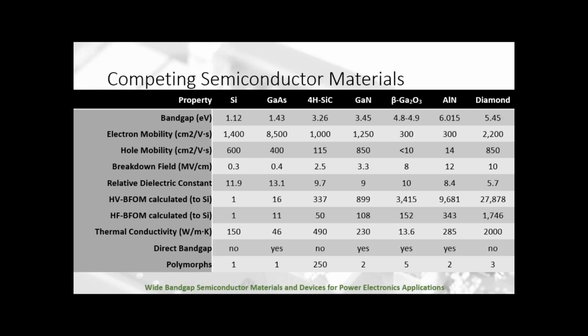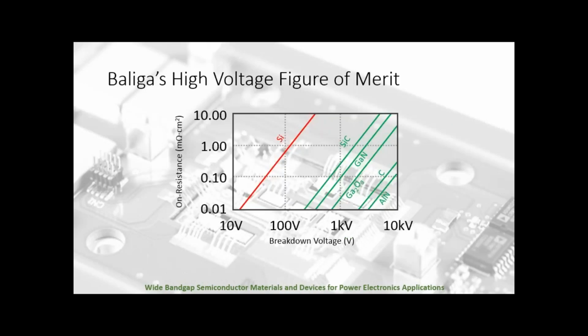Here, this is a much higher number that's typically used for gallium nitride. You see 100, 120, 110, 130, and that's because those measurements are on highly defective gallium nitride. But at the end of the day, you see these big figures of merit kind of go up as you go to the right. So these materials are increasingly of interest for power electronics because that's what that figure of merit's all about. And here is a plot of the on resistance versus breakdown voltage on a log-log plot that the high voltage Baliga's figure of merit speaks right to.